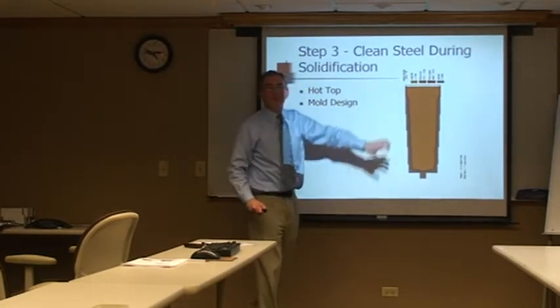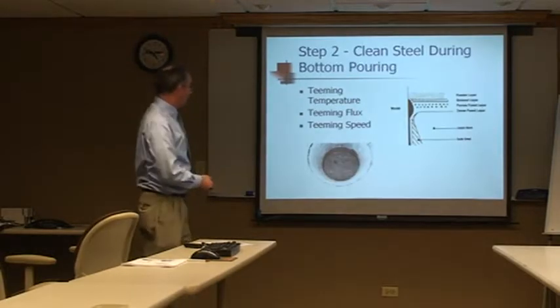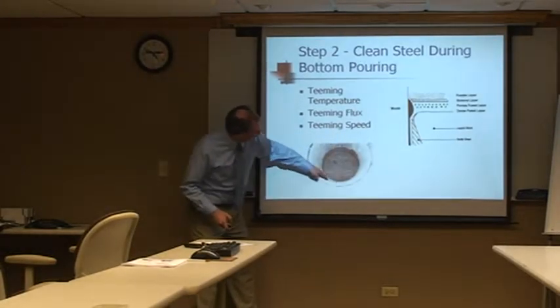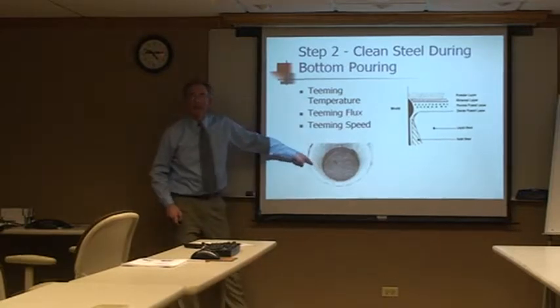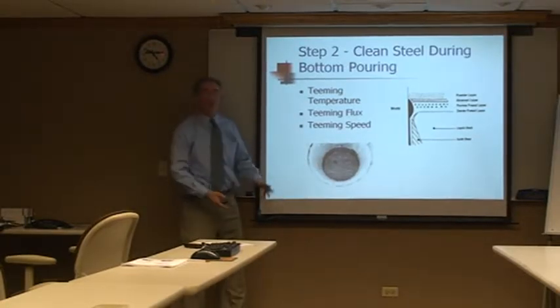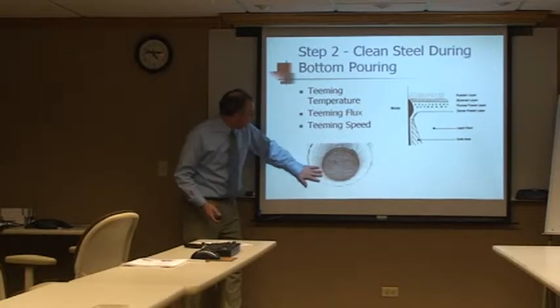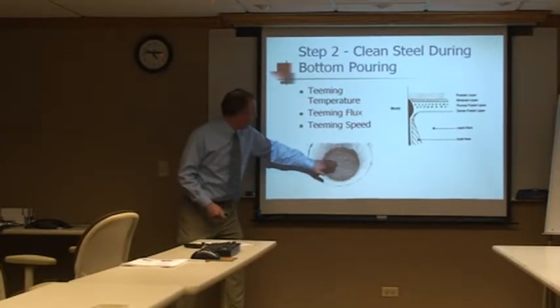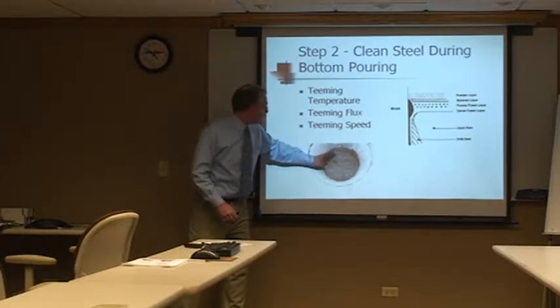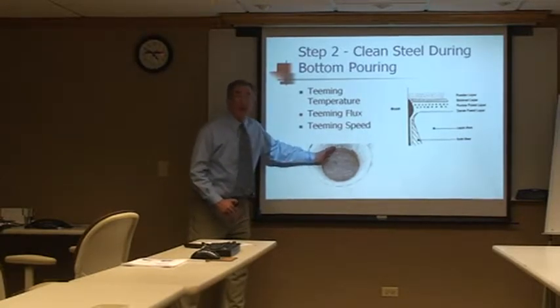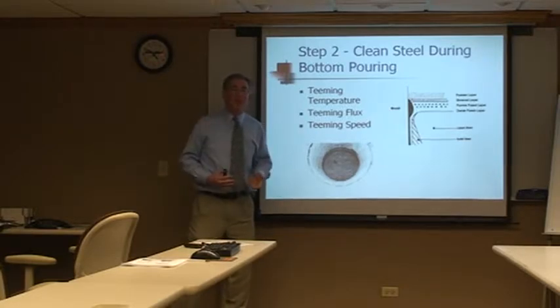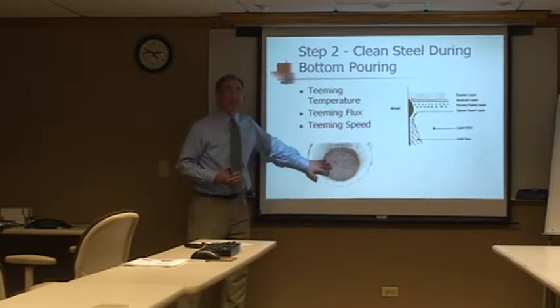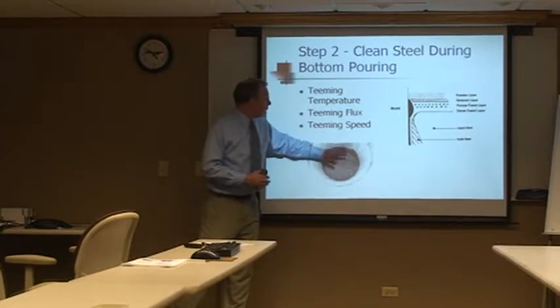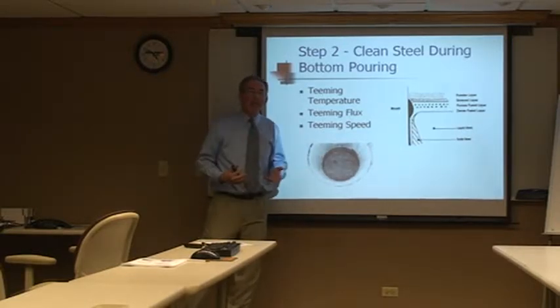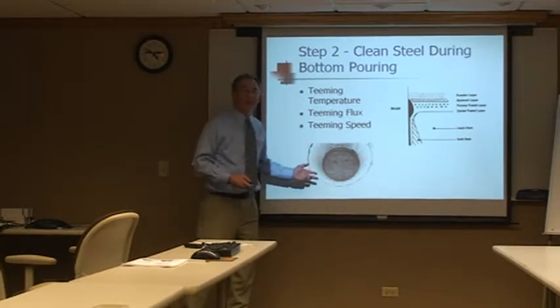The reason is because we use what's called a hot top. If you look here, you see these boards that are wrapped around here. I don't know if you guys can appreciate that or not. These boards, as the steel fills up into the mold, as soon as it hits these boards, these are made out of an alumina-based refractory, the boards are going to begin to burn. Now some can insulate, but some will burn. And when they burn, it gives off heat. And that heat slows the solidification process down. It's called an exothermic hot top or an insulating hot top.